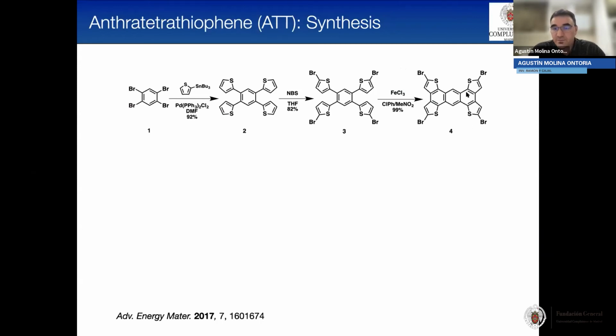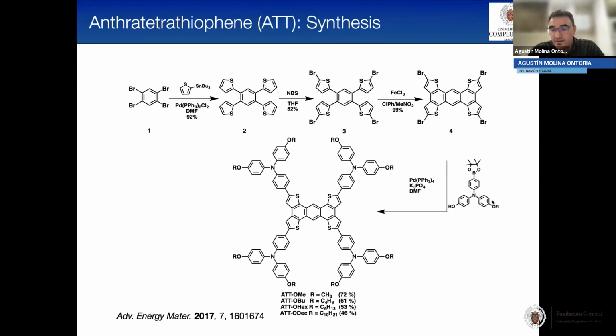For getting molecule 4, it is quite straightforward. And more importantly, no column chromatography was needed. Just by washing and precipitating, you can obtain 4 on a gram scale. So we started with this tetrabromobenzene. We performed a 4-fold Stille coupling, bromination at the alpha position of the thiophene rings, and finally a Scholl reaction in the presence of iron chloride. Then we introduced the triphenylamines with different lengths of alkyl chains by a 4-fold Suzuki coupling.